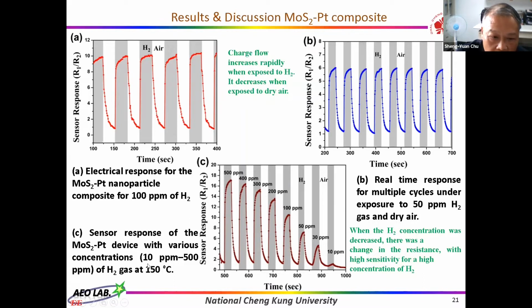Figure C shows the sensor response of the MoS2-Pt device with various concentrations from 10 ppm up to 500 ppm of hydrogen gas at 150 degrees. We can see from this figure, when the H2 concentration was decreased, there was a change in the resistance, with high sensitivity for high concentrations of hydrogen.